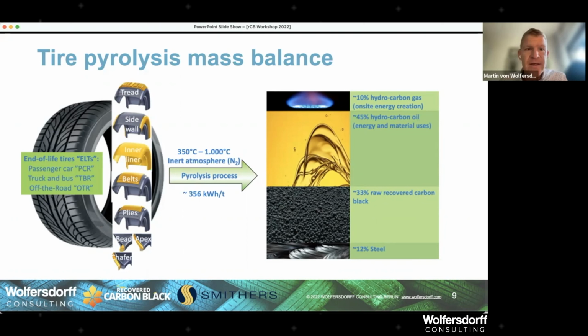It could be anything. The important thing is, and every tire, as you can see in the left image, is made of different sections. The tread is one of the predominant sections. Inner liner and sidewall are big. Then it goes into belts and the plies. The plies is where the textile is. The belts is where steel is. So this is showing a passenger car tire, because truck tires don't have the textile, but they have double the amount of steel. And then you have the very small compounds in the bead, apex, and the chafer. Truck tires are even more complex than that, might have up to 14 different bespoke sections.